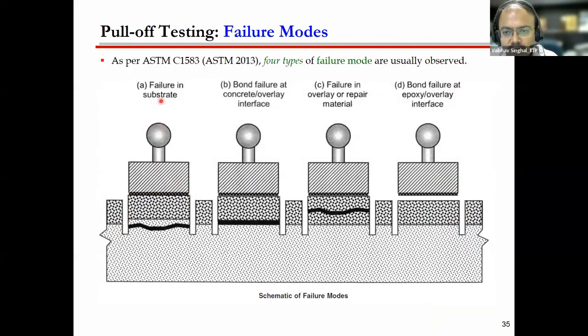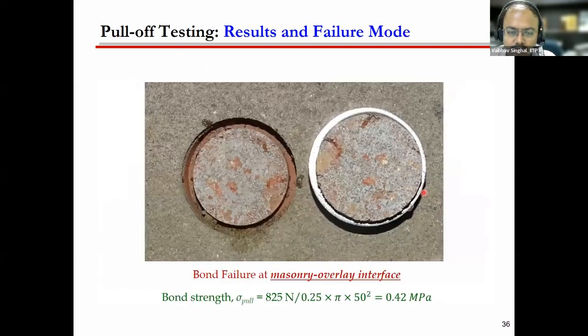And then we notice the different failure modes, and the strength at which this fails is divided by the total area. You will get the bond strength. Now here also you can have different failure modes. So the first failure mode is in the substrate. If the failure is in the substrate, you can say that the bonding is good. There can be a failure between the cementitious matrix and the substrate material. You can have a failure between the overlay, or in the matrix itself. And then you can have also the failure between the attachment and the surface. Now this is one of the failure modes which we have seen. I will show you some more failure modes.